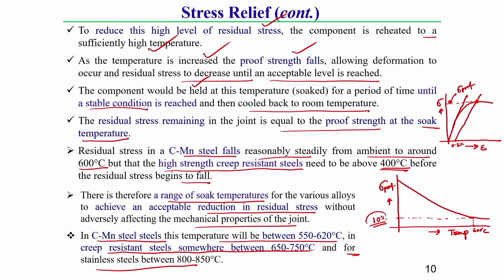So, at this temperature level, that means if we raise the weldment specimen to a temperature of this level, then whatever the proof stress is at this temperature level, that proof stress magnitude will remain as the residual stress after this stress relief heat treatment operation. What I am telling, understand? This you should keep in mind.